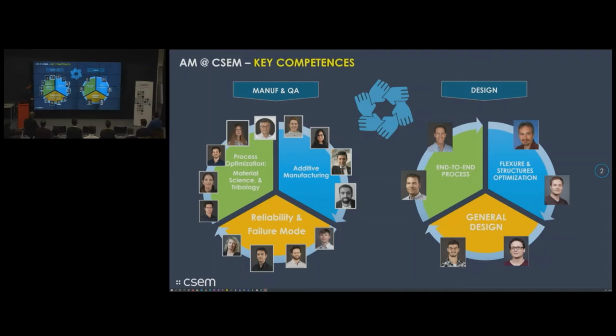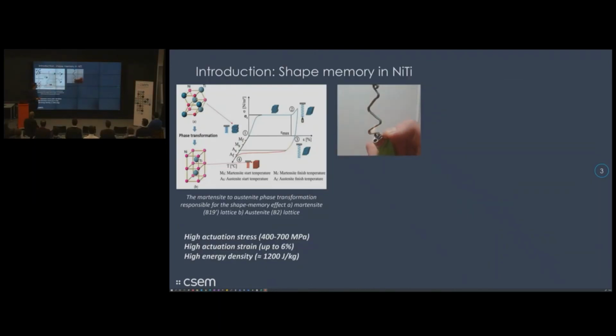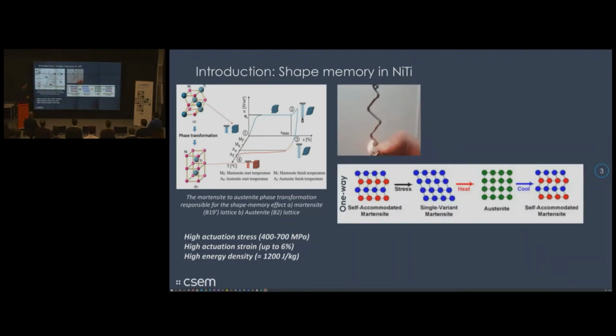So to start with, I don't go too big into the details. It was already explained what shape memory alloys are and how they work. I will just basically repeat that we take the advantage of the solid state phase transformation between martensite and austenite phase, and particularly the fact that martensite actually exists in two different forms. One that we call the self-accommodating martensite. It's the one that we obtain when we, for example, do laser powder bed fusion, and the material is at a high temperature in austenite.